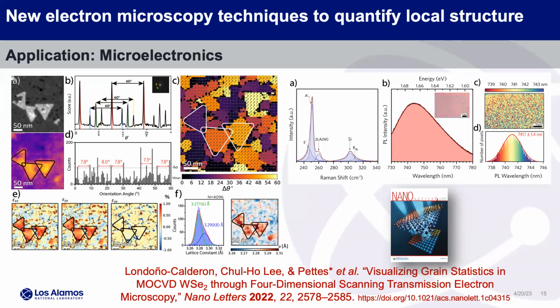These are nucleated over crystals. This is a monolayer, and this is the second layer that's growing on it. We can get statistics on this to show that you can actually calculate the misorientation in a statistical way. For the 2D material, it's kind of expected that you could do this, but we wanted to show it because no one had really shown automated crystal orientation mapping from electron diffraction before. Again, this is in collaboration with our colleagues at Berkeley. But this is really nice.